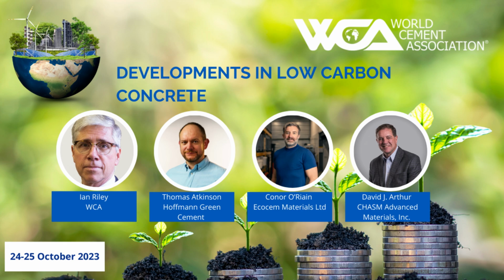I'll bring to your attention more than 70% increase in the flexural strength of the mortar samples and almost 30% increase in the early compression strength. These two properties are very meaningful for low carbon and low cost cement. We have obtained similar results for various types of cements across different parts of the world.